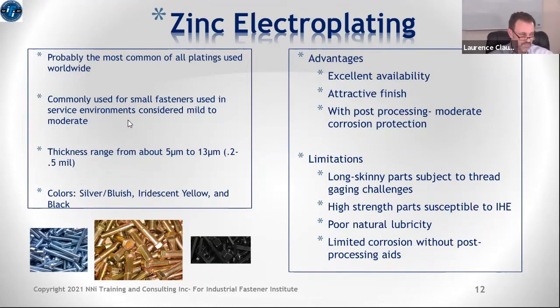And as manufacturers and suppliers of fasteners, you tend to assess your risk of how much risk the part has for hydrogen embrittlement. And if it's a high strength part and you're using a zinc electroplating finish on it, it is at higher risk, susceptible to internal hydrogen embrittlement.